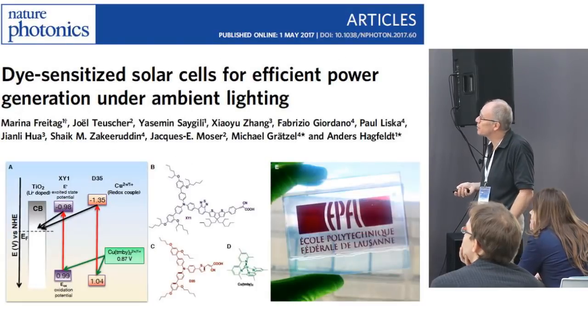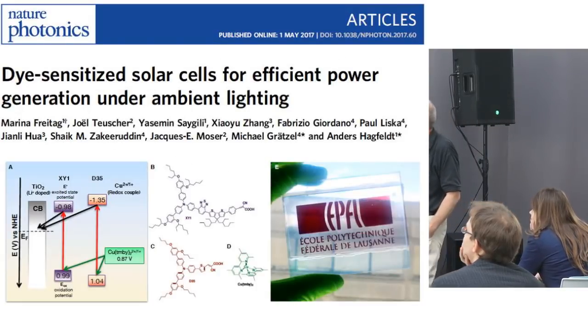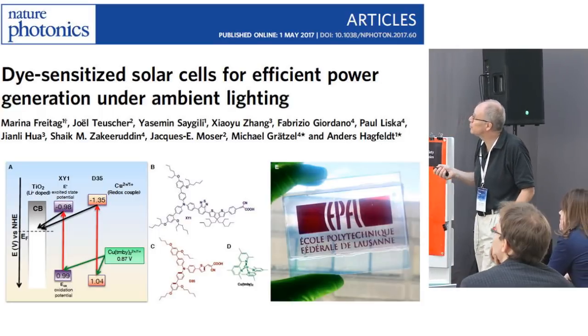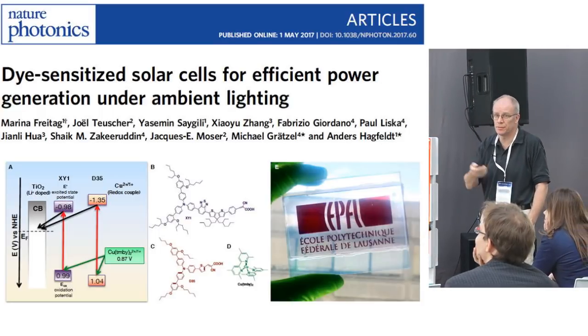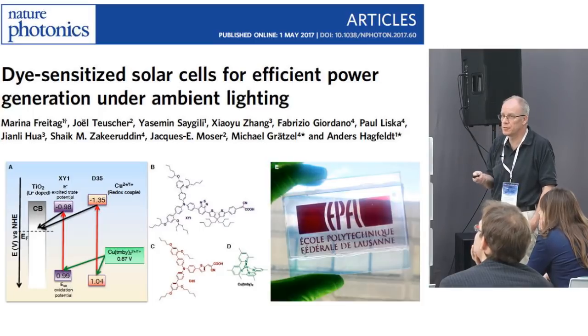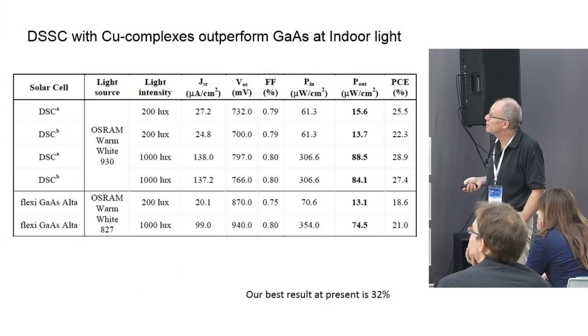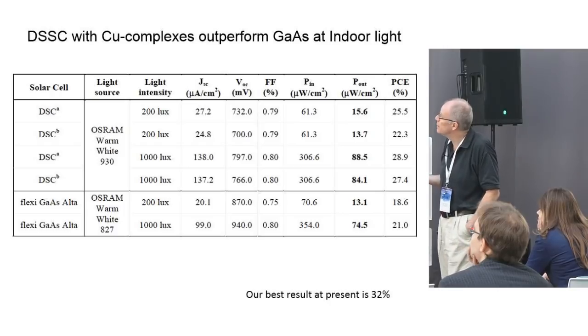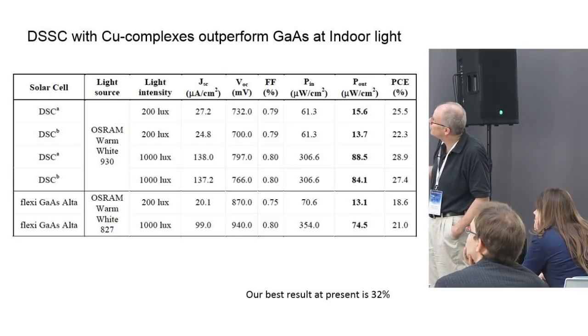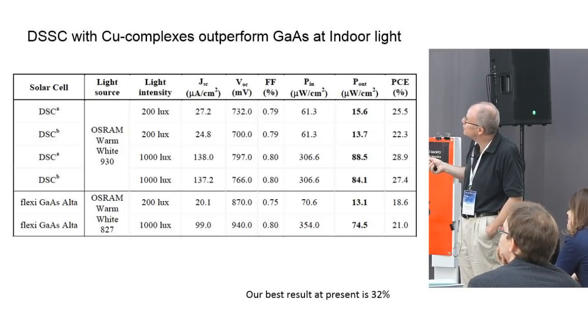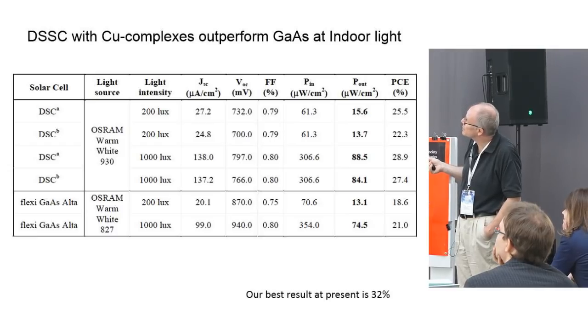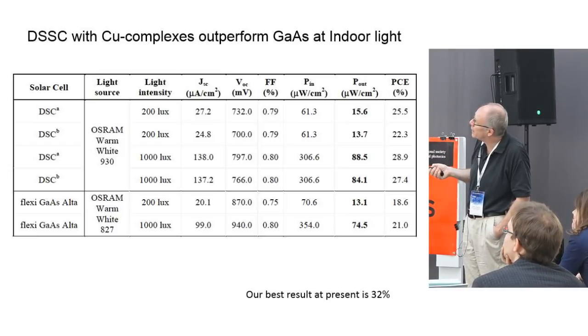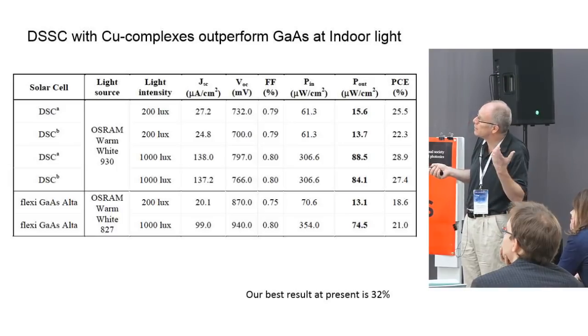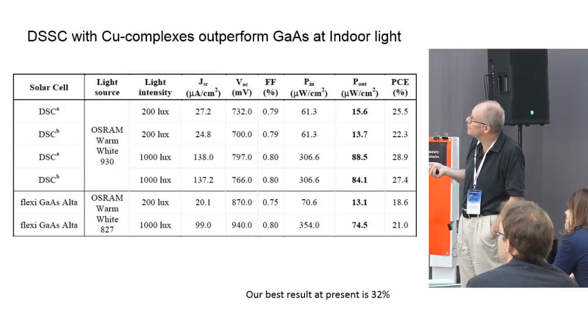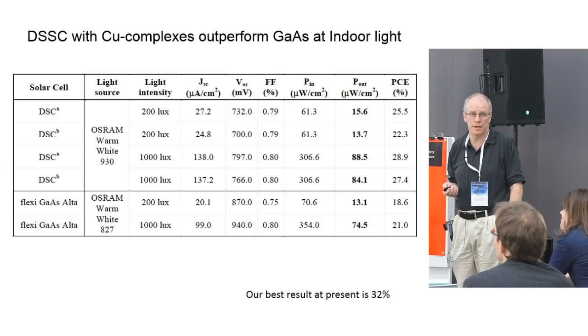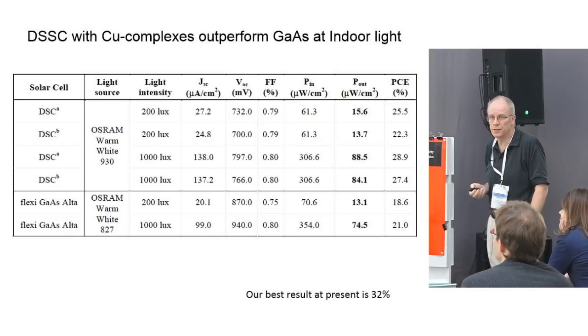One interesting aspect of this copper complex and organic dyes is that they work very well for indoor light, diffuse light. So if you have sensors indoor and so on to replace batteries, for example. There the dye-sensitized cell is giving the highest. This is the power output in microwatt per square centimeter, 15 microwatt per square centimeter with a fluorescent lamp at 200 lux. That's the unit for light intensity. This is what you have in here, I would say, about in light intensity, 200 lux.